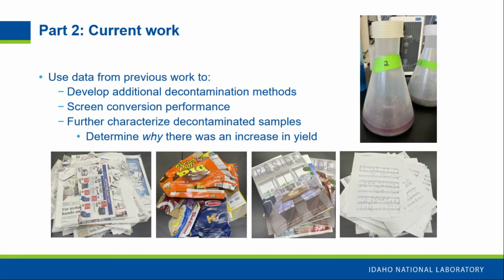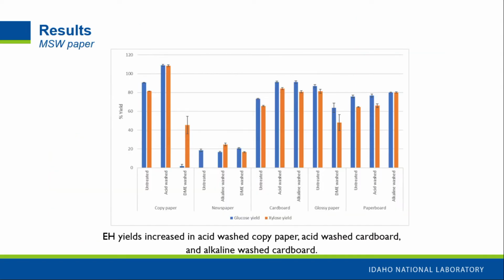And so the second part now is just focusing on some current work. This is follow-up work based on the results that we found in the paper that I was just talking about. So we want to use our data from our previous work to develop additional methods of decontamination, screen their conversion performance, and then further characterize the decontaminated samples and determine why there was or was not a yield increase. The most important thing from this, I'll just point out. We screened a couple different wash processes: acid washing and alkaline washing, and then we also used DME as well for paper.